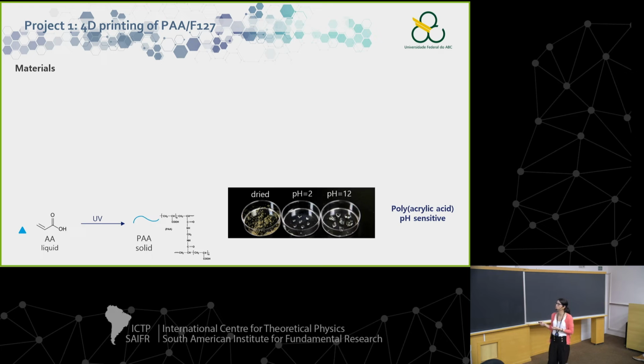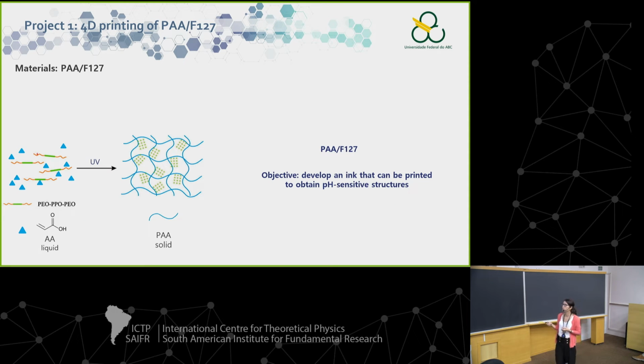So we've selected polyacrylic acid, which is pH-sensitive. Here you can see this polymer shrinks at low pH. At high pH, it swells. And just for the history, it is a polymer that is used in baby diapers. So for those who have babies, this hydrogel is saving our lives. So what we do is mix Pluronic and acrylic acid, the monomer. Then we expect it to gellify when we increase the temperature. Then we print it, and once the structure is printed, we apply UV light, so we get polyacrylic acid.